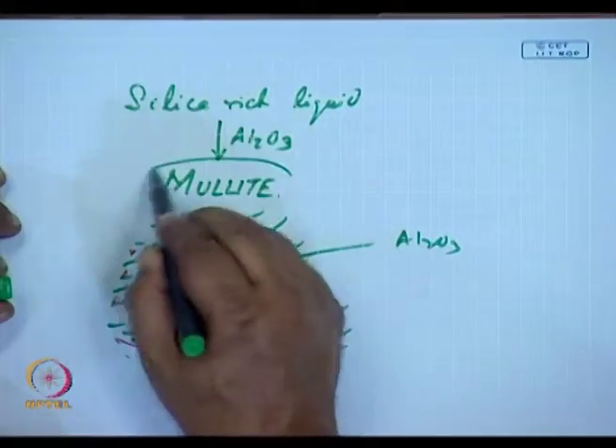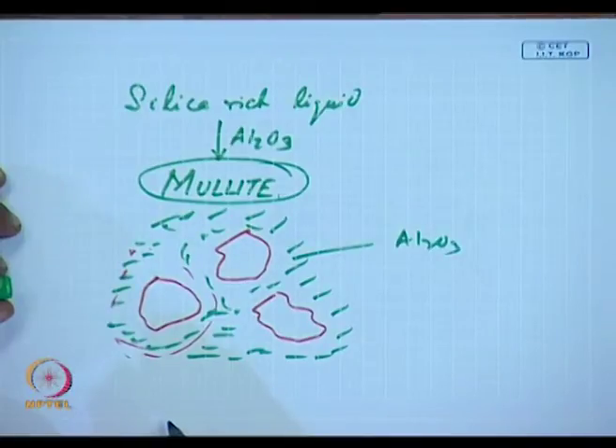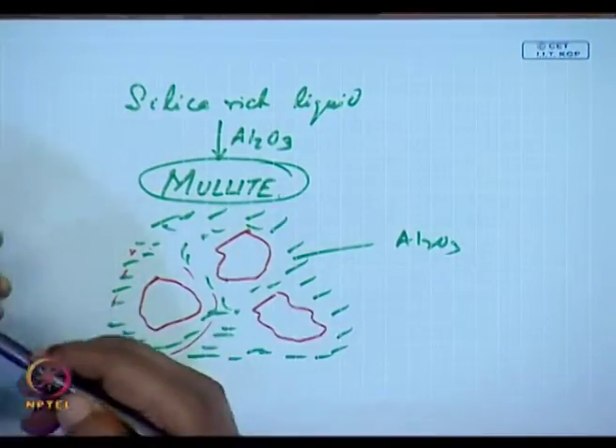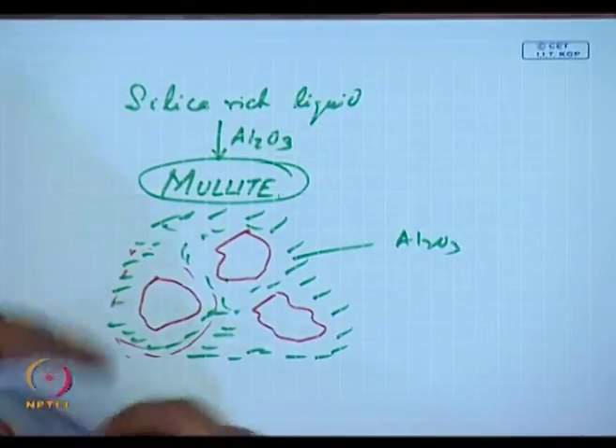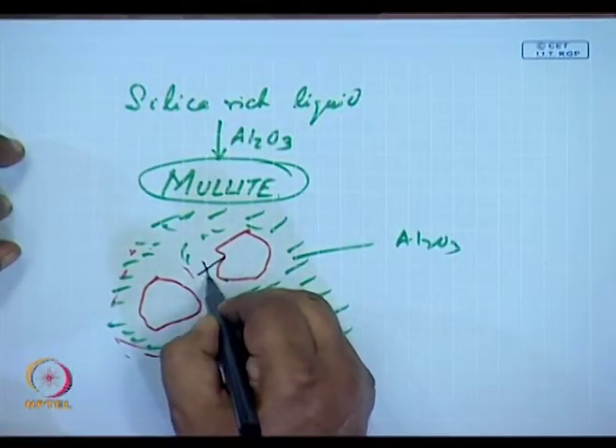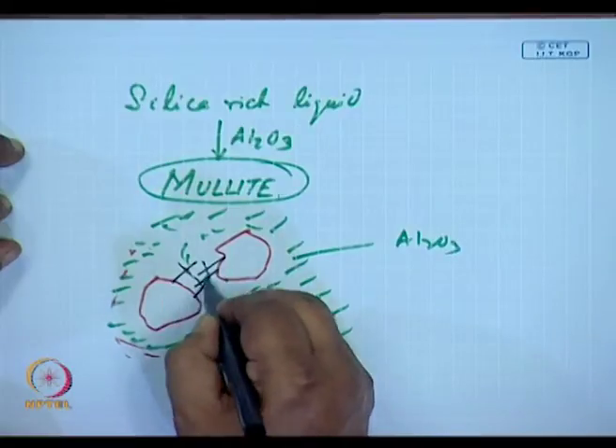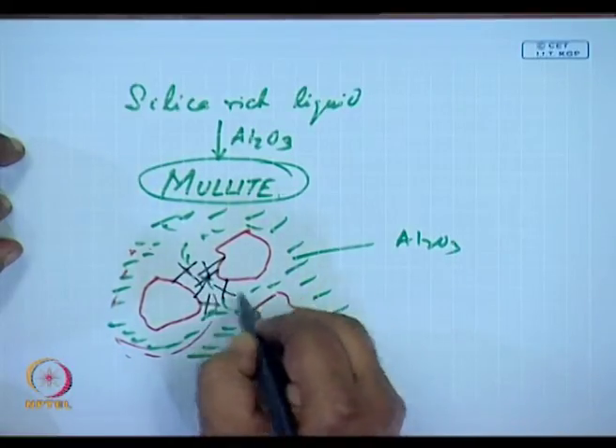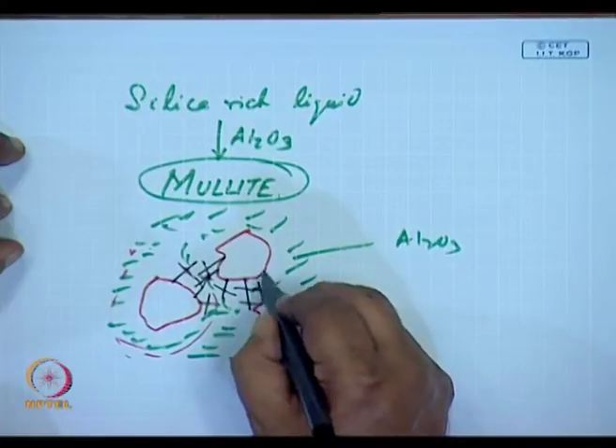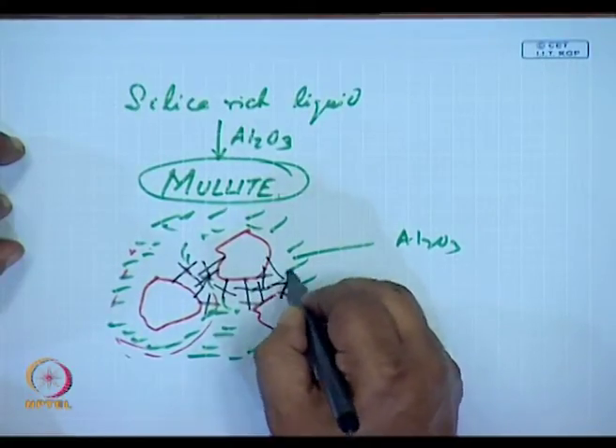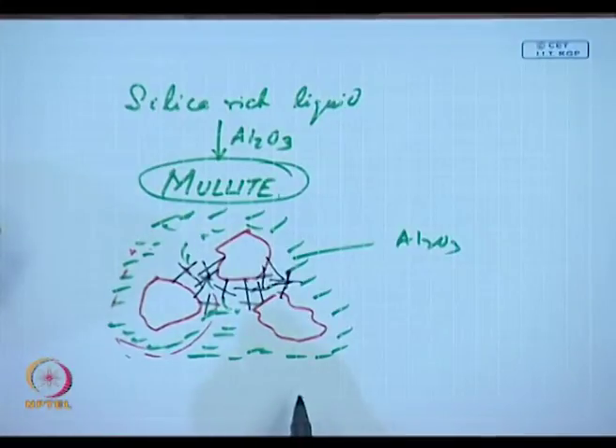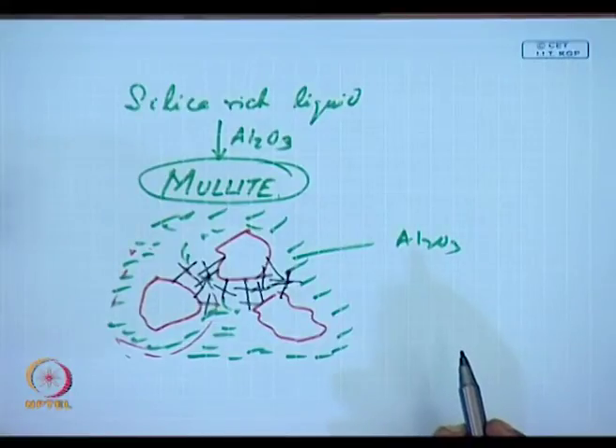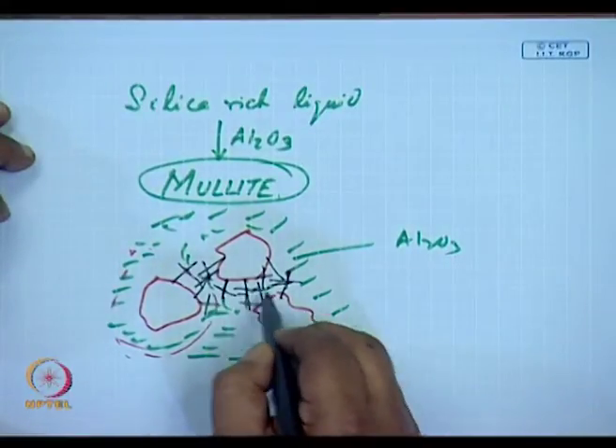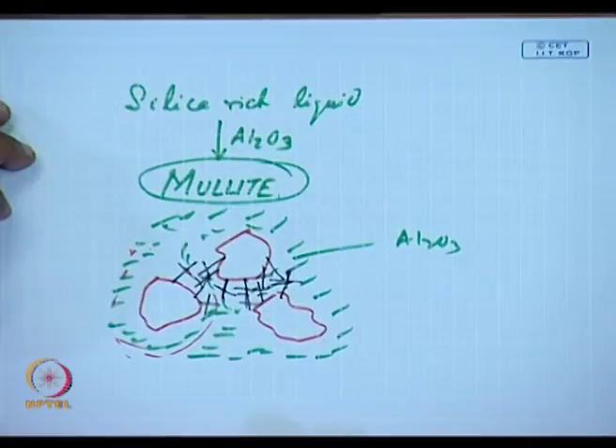The liquid would get supersaturated with mullite. This mullite would precipitate. Most of these growths are dendritic. As a result, lot of entangling happens, and the structure will have, the liquid will have a lot of mullitic grains out here.